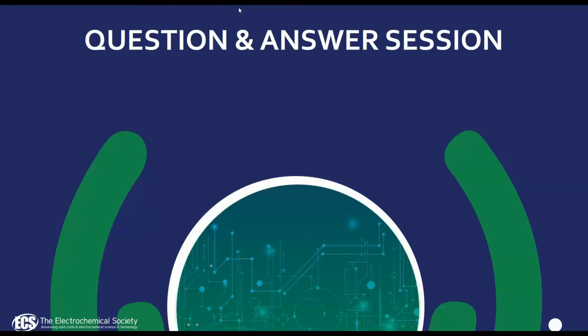We're really talking about fast redox processes. You have transition metal ion valency changes. It's just that the diffusion is so fast, it looks like a capacitive response in the nomenclature and analysis that someone like Bruce Dunn would do, right? So if you do a scan rate dependence, you get this exponent of 1. That just means there's no diffusion contribution to the overpotential you're measuring. So that's an easy one to answer based on what David already told us.